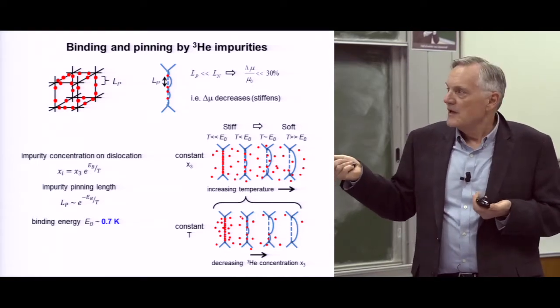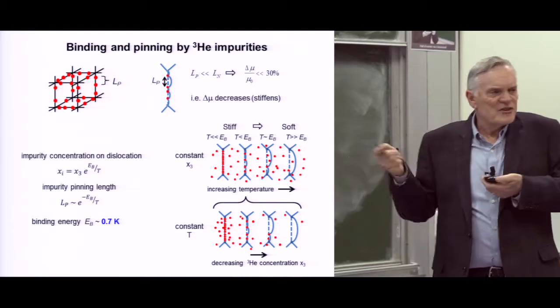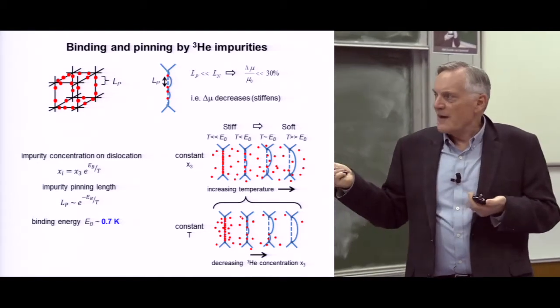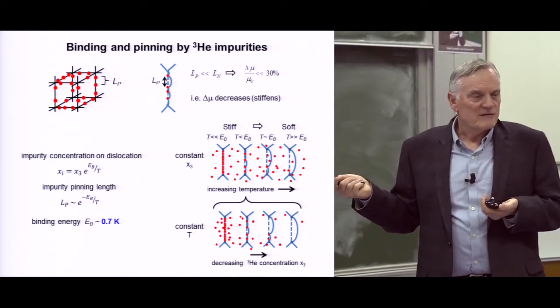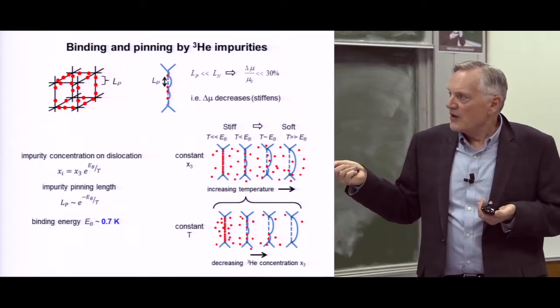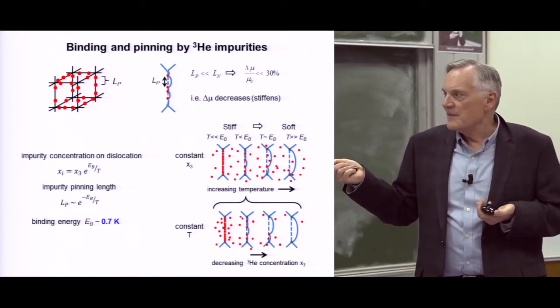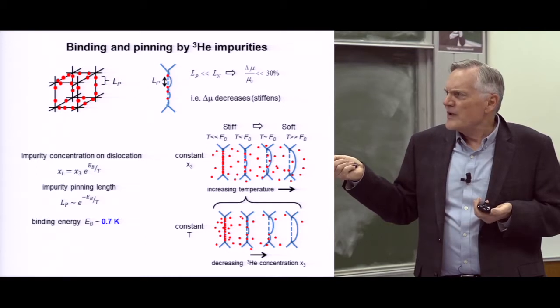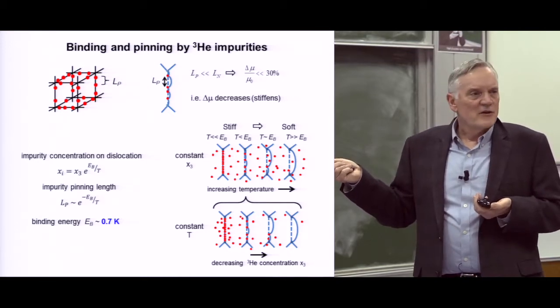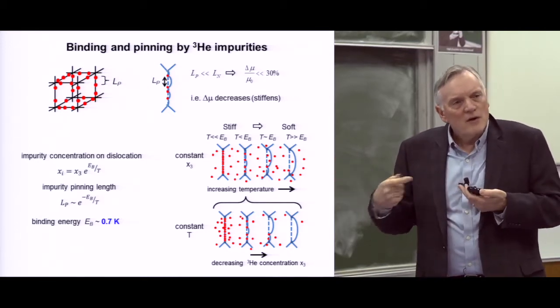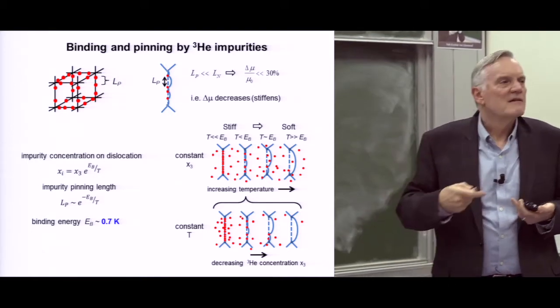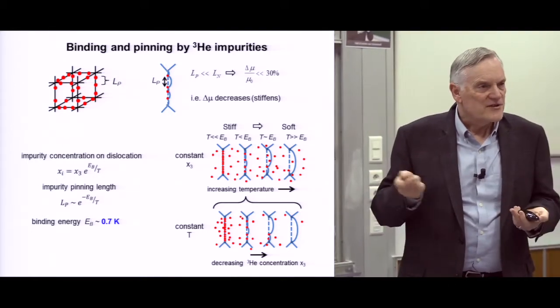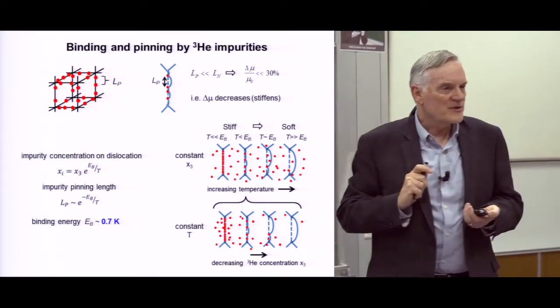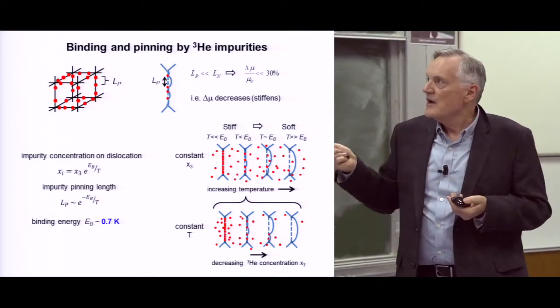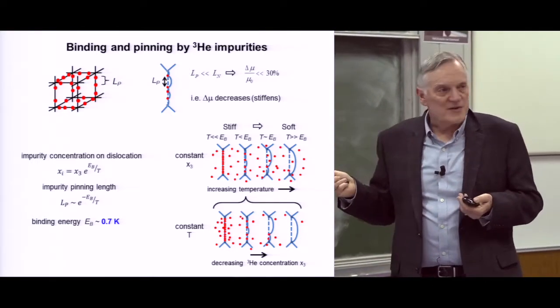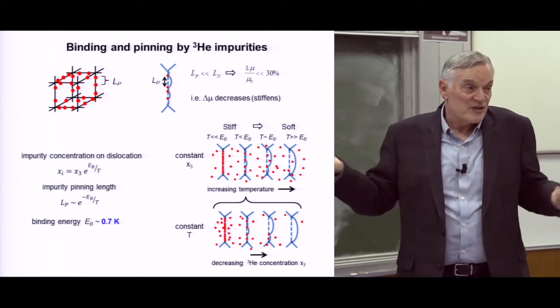It softens the crystal. If you think about going to low temperature now, and say, what happens if I change the helium-3 concentration at some fixed temperature? Well, if you've got lots of helium-3 present in general, it'll be pinned. But at the same temperature, if you're at really, really low concentrations, they're hardly going to be pinned. So as you go to lower helium-3 concentrations, it becomes free to move and soft again. So that shifts everything down to lower temperature, which is the effect we saw with the helium-3. So the helium-3 impurities are associated with that. We know that because we change it and it changes.